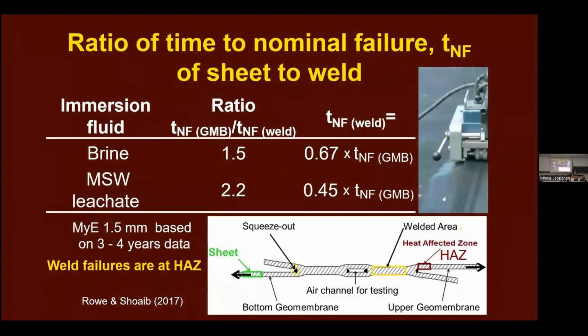When I say welds are the weak link, let's take a weld and let's age it in parallel with the sheet and see what happens. And the ratio of the time to nominal failure of the sheet divided by that of the weld is shown here in a brine solution and a municipal solid waste solution. Or put another way, the life of the weld is, in this case, 67% of that of the sheet, in this case, 45% of that of the sheet, because you do some damage in doing that weld. Now, can you do less damage? The answer is yes.